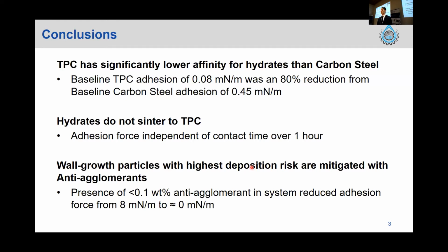But it was shown that those could be well mitigated with the presence of anti-agglomerants, and in fact less than 0.1 weight % anti-agglomerant in the system was able to completely reduce that adhesion force from 8 millinewtons per meter to roughly 0, or below the detection limits of our apparatus.